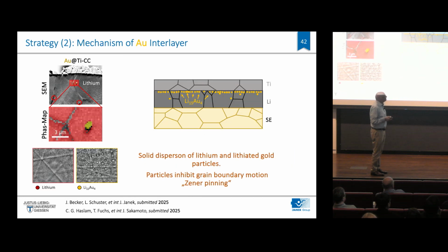How does it work? With the gold, we have, meanwhile, a paper that was just accepted. The gold nanoparticles at the interlayer, if you grow lithium, really move into the growing lithium film. We even can identify them by the Kikuchi pattern, so they form a Li15Au4 intermetallic phase. And it's called Zener pinning: they tend to immobilize the grain boundaries, or they influence the motion of the grain boundaries and the grain growth. So, in fact, particles can change your microstructure, of course.